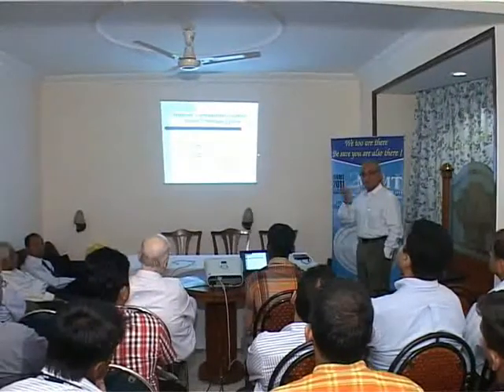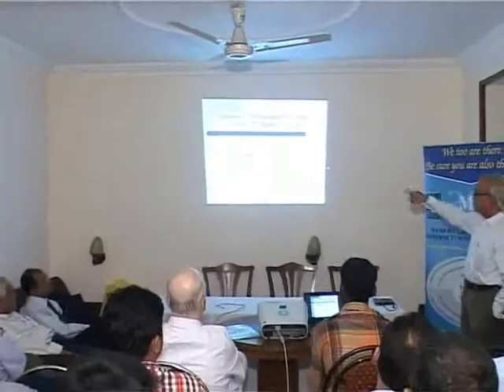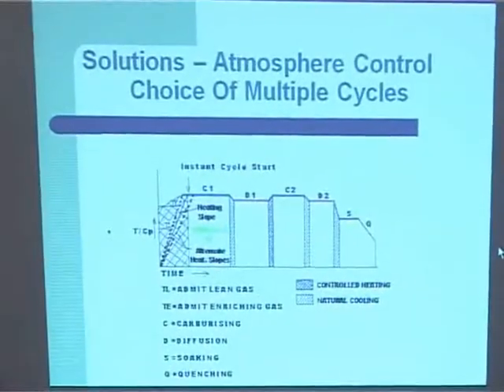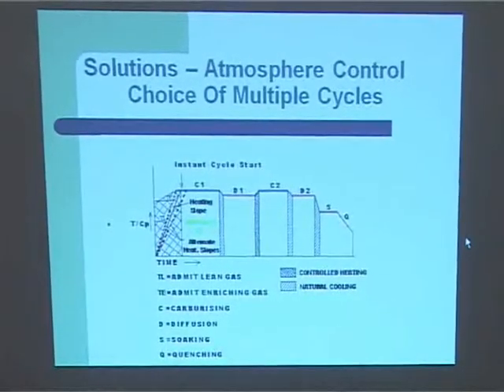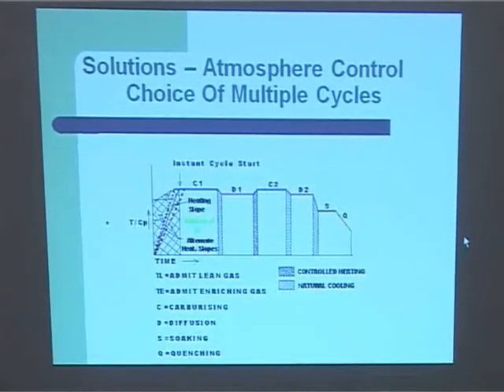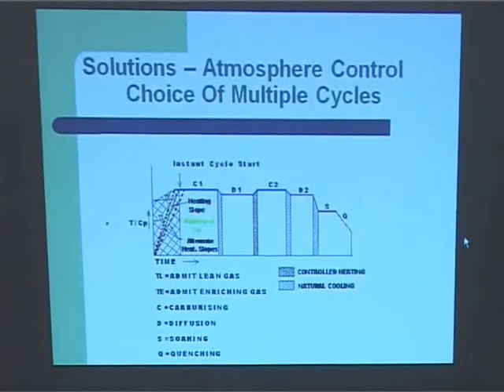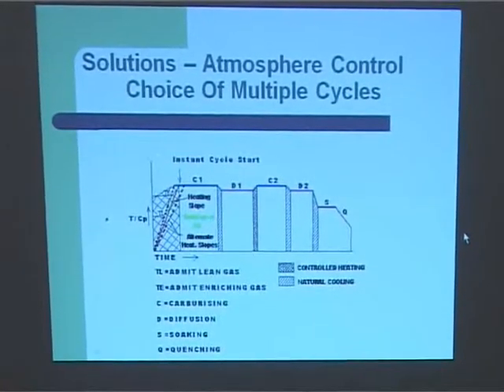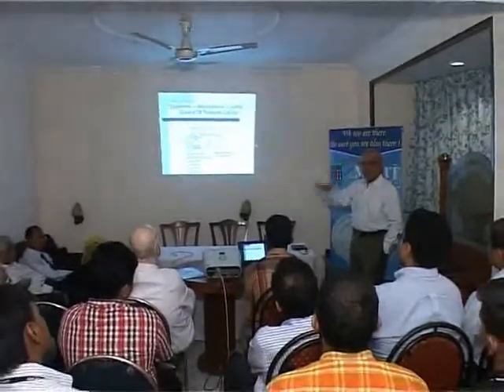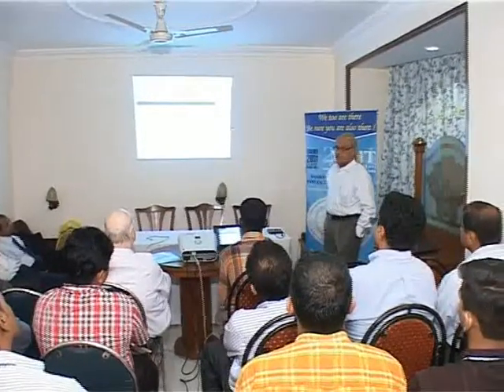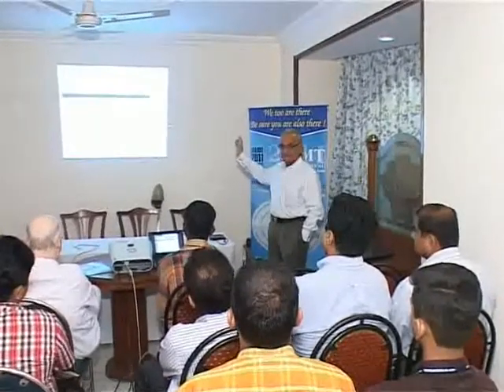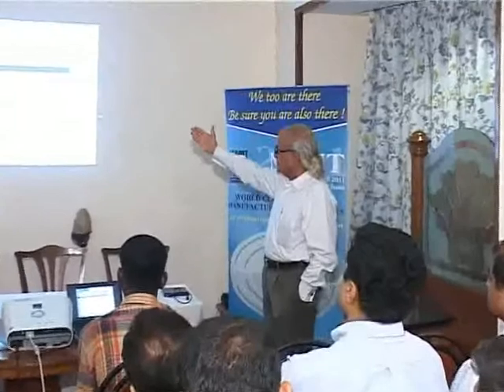This is a typical cycle, all of you I think know it, I need not elaborate on that. The only thing I try to show is what is a multiple segment, and if you see the initial stages, there are two dotted curves and one red line curve. The red line curve is the ideal heating slope and the dotted one on this side shows very slow heating. Either your heating element capacity is not okay, or the heating elements are too powerful. Too powerful means you are pushing the furnace, and at that stage you are consuming a lot of electricity and the current loading of the heating element goes very high, and therefore the life of the heating elements gets shortened. Super Kantal, A1, whatever heating element you use, if you are forcing a furnace, the heating element life gets reduced, and if you are heating it very slowly, your productivity suffers. And you have got multiple segments: carburizing 1, diffusion 1, carburizing 2, diffusion 2, soaking and so on. Next.